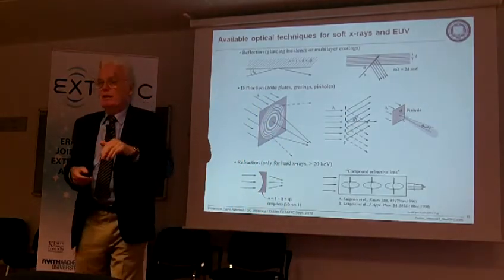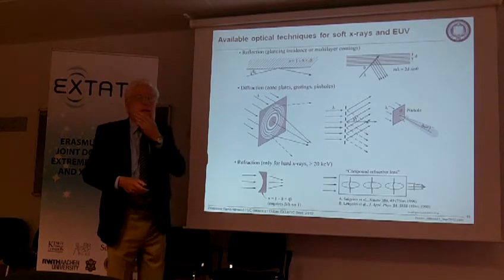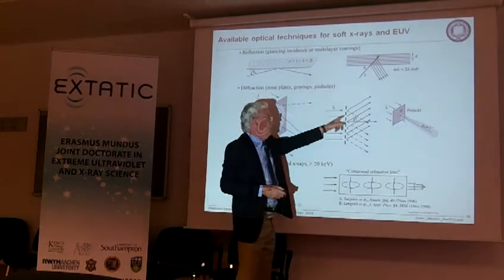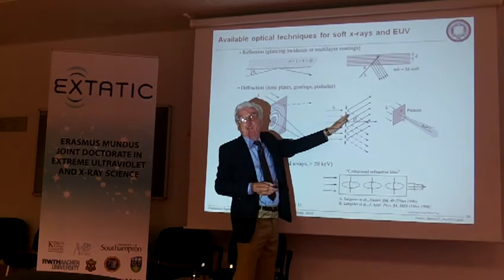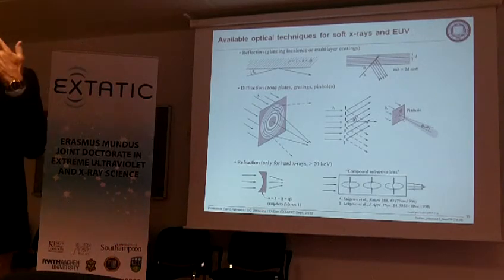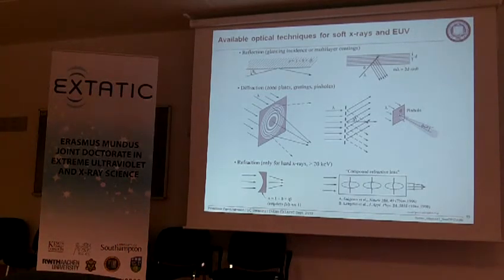And in fact, in the X-ray region, at harder photon energies, you get into a different problem, but you can make structures which are just phase effect structures, where absorption plays some role, but the phase effect is much more important. So I have a colleague who is working now on making zone plates for 25 to 30 keV, and the efficiencies are going to be much higher, like 30%. In fact, he has made them and used them in some focusing experiments. Those are good questions. Thank you. That brought up some additional points.